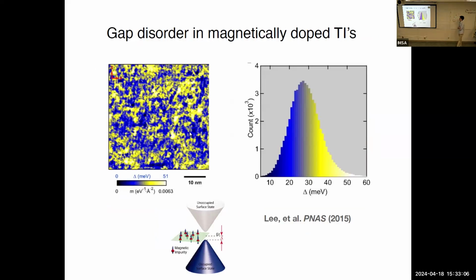But what was even more important is we came across this paper. These authors measured this magnetic gap, the spatial fluctuations of this gap, using STM. This shows the magnetic gap in the Dirac cone as a function of x and y. As you can see, there is a very large distribution, and this histogram displays the overall distribution of this gap. Compared to 3D TIs, where you can just apply a magnetic field and have Landau levels, you just have one gap. But in this case, because of difficulties with doping with chromium, you can never get a single well-defined gap, and you will always have this very wide spatial fluctuation of these gaps.